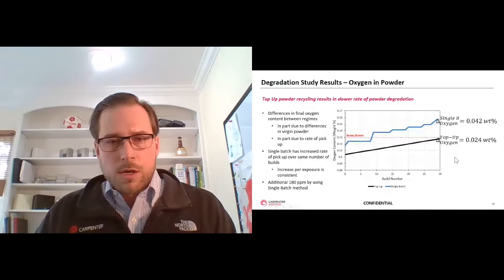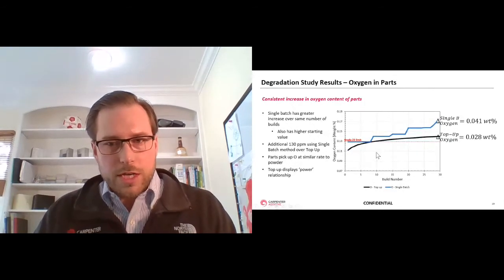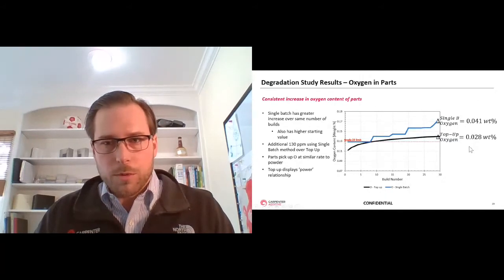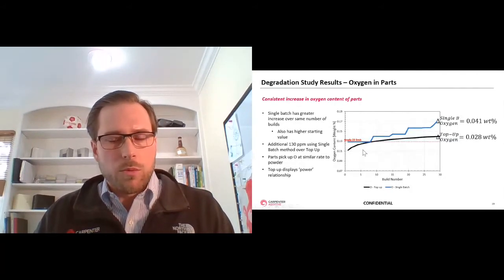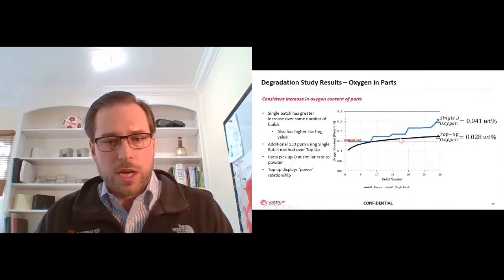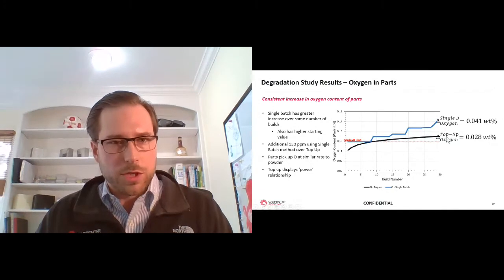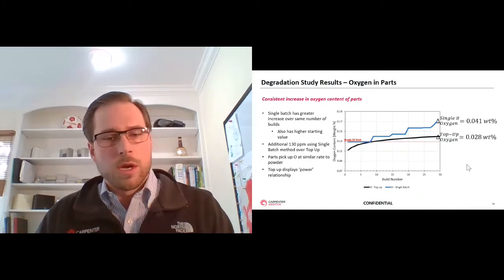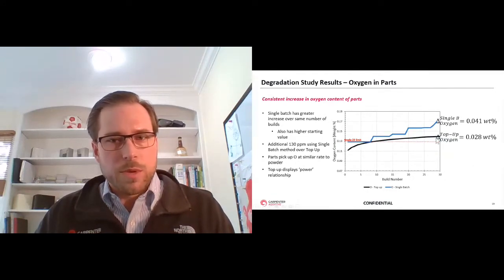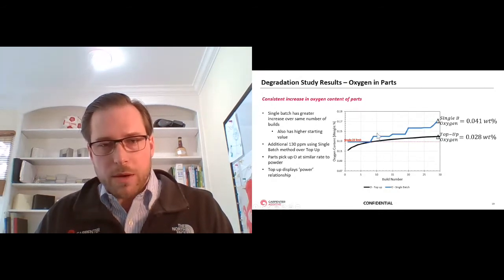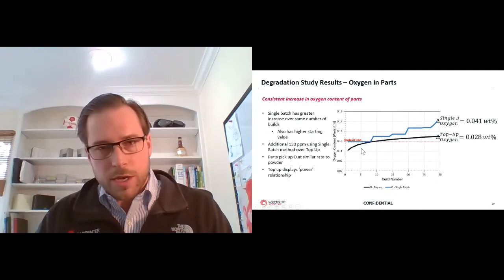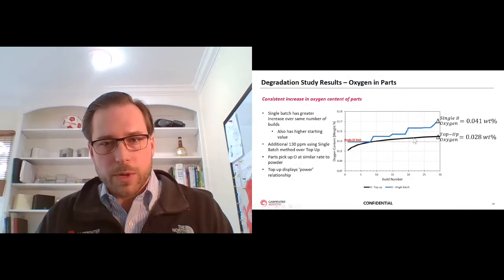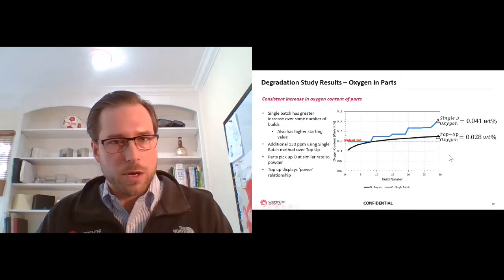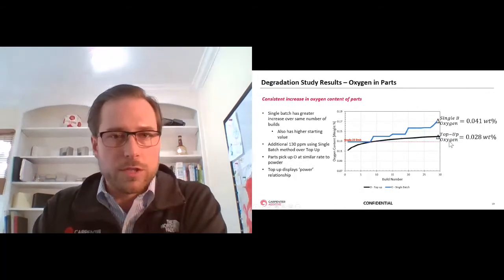Okay. So then when we look at what happens to the oxygen content in the parts, it's a similar story, almost double, not quite in this scenario. But what we see is us reaching a sort of equilibrium state with the top up methodology in terms of the oxygen content in parts, which is really quite interesting, because typically people wouldn't be using grade 23 powder to build grade 23 parts, but in the medical industry that is often the specification. In aerospace, it may mean that using this grade 23 powder gives you a much longer life making grade 5 parts. So it's very interesting.